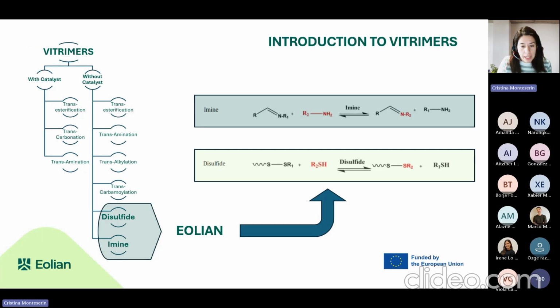So vitrimers can be synthesized through different routes, depending on the type of dynamic bond used. In many cases, a catalyst is needed to activate the dynamic covalent exchange, while other chemistries can operate without one. This slide summarizes the main dynamic chemistries available for designing these vitrimer networks. And within the EOLIAN project, we focus specifically on imine and disulfide chemistries.